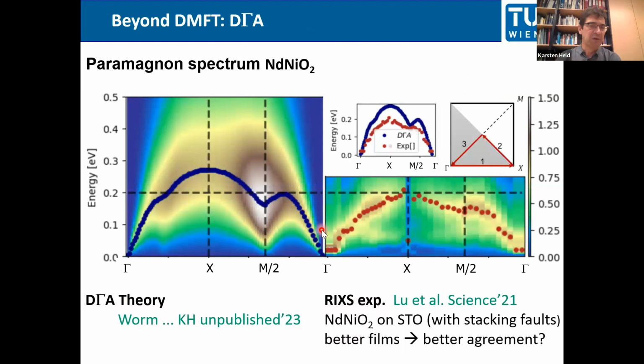We can also compare the strength of the antiferromagnetic spin fluctuations. That is the theory for the very same calculations we did before. And that's the experiment. Here you compare the blue and the red maxima, and it nicely agrees, in particular if you consider that these were still the old films with the stacking faults and the smaller TCs and larger resistivities. So depending on what kind of disorder you have, if you have a more local disorder, you would expect that the antiferromagnetic coupling and therefore the width of the paramagnon dispersion is coming down. So the question is whether the better films will also yield a better agreement, or whether other disorder mechanisms are at play here.